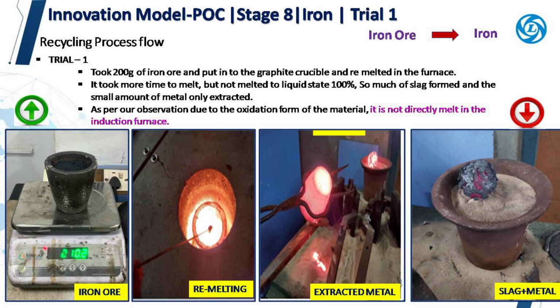We made a trial one. We took 200 gram of iron ore, placed it in a graphite crucible and attempted remelting in the furnace. The material required extended heating time but did not achieve a fully liquid state. A significant amount of slag was formed and only a small quantity of metal was extracted. Based on our observation, the oxidized nature of the material prevented it from melting directly in the induction furnace.